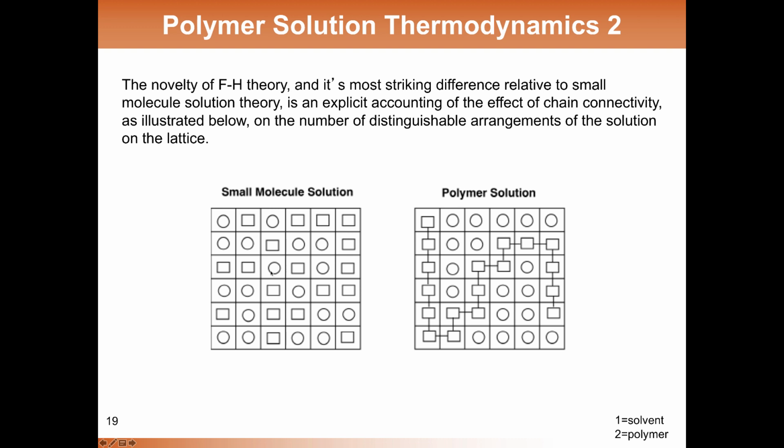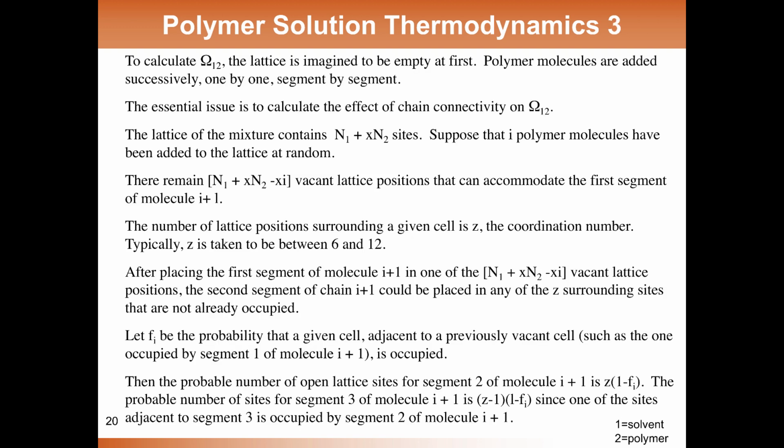In the monomeric state, the delta S of mixing is just so high that the monomer and solvent will mix together. But when you start to polymerize the monomer to form polymer chains, the delta S of mixing goes way down, and you may get to a situation where the polymer actually phase separates during polymerization, and that's the foundational basis for this.